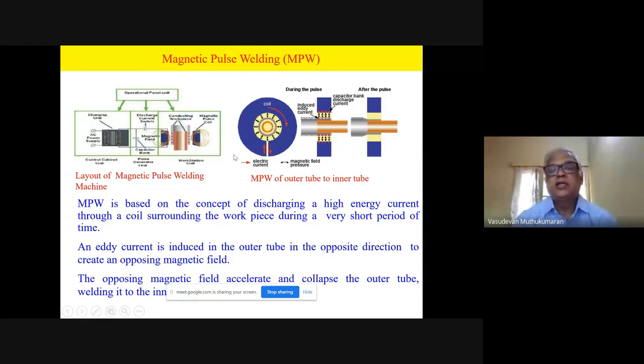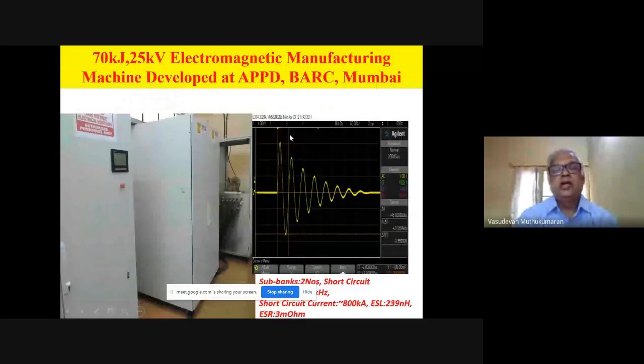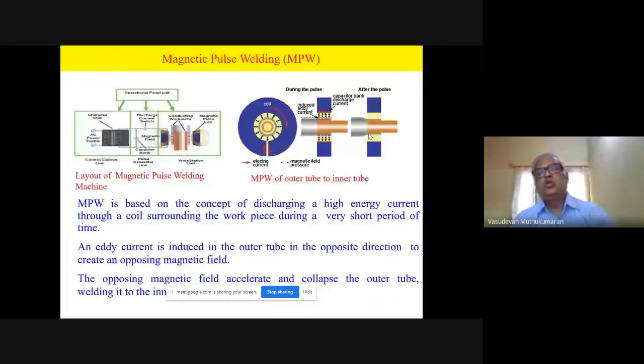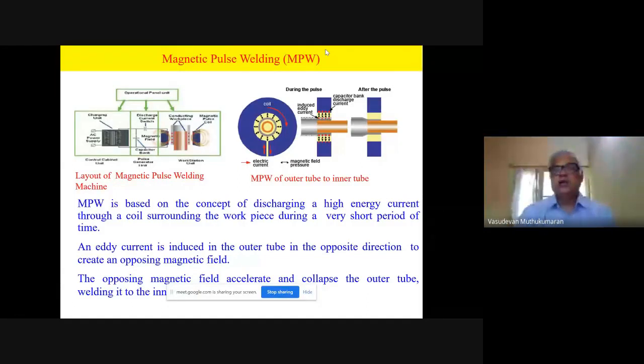So when a current is passed in a short time through the coil, a magnetic field is induced in the current carrying coil. There is also eddy current introduced in the outer tube. Then an opposing magnetic field is generated. So the two opposing magnetic fields between the coil and the outer tube repel each other. So it accelerates the outer tube to make an impact on the inner tube. That's how, because the impact velocity is very huge, plastic deformation forms the bond. This exactly we are using for this tube, which is a clad tube. This piece is an end plug. We are able to weld successfully using this technology.